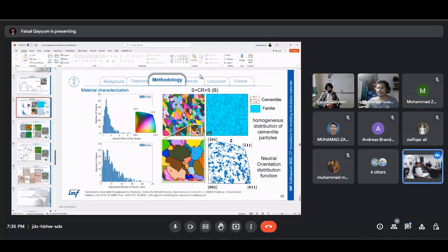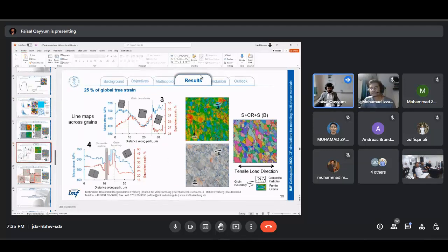In this simulation, does the actual direction of the grain play a role? Does it influence the plasticity? Yes. So here we see an example. What I did here is, you will see that I plotted this graph along this line. You see this? Mm-hmm. So when we plot the results from this line, they're shown here. These lines represent the grain boundaries, and across the grain boundaries there is another grain, and here I have shown them with different cubic orientations to show the orientation of these grains in 3D space. And here you will see that when we go across these grains, the stresses and strains change.